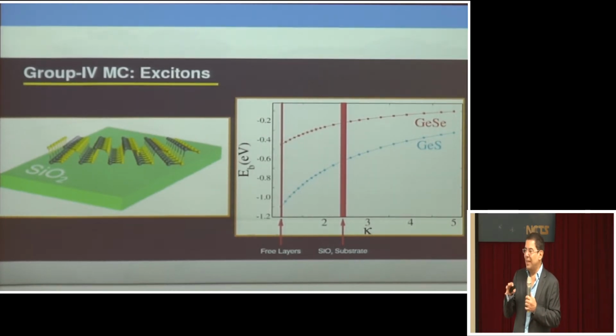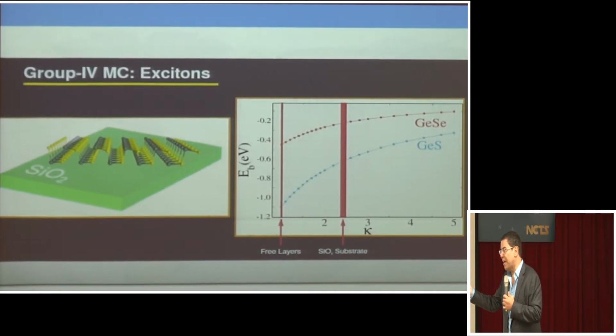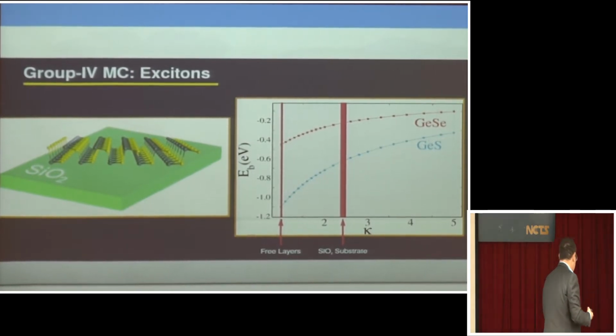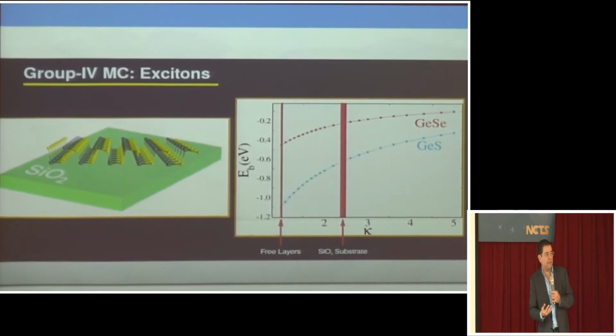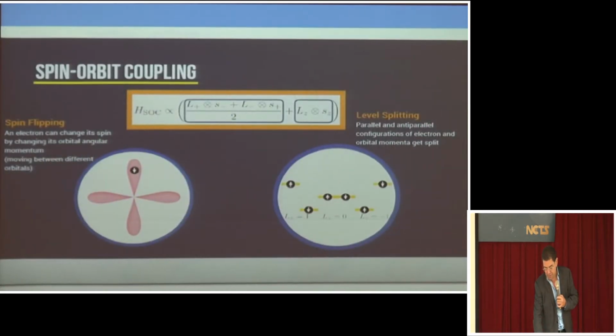So, interesting thing, now you can control the exciton energy by selecting the substrate. If you do mica, you get one thing. If you do silicon oxide, you get something else. If you put boron nitride, you get something else. So there is now this possibility of controlling the excitonic states from the outside by just changing the substrate where you actually deposit the material.